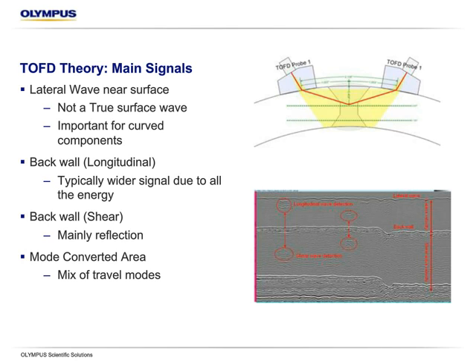It's very important for curved components, especially as we can see in the picture a little bit. It might be a little bit hard to see, but if we have a curvature to our component, the more obtuse that gets, we're going to have a small area of uninspected area on top of the fact that it's not a true surface wave. There's always, at minimum, a dead zone associated with TOFD, and we'll look at that and how to adjust it a little bit.